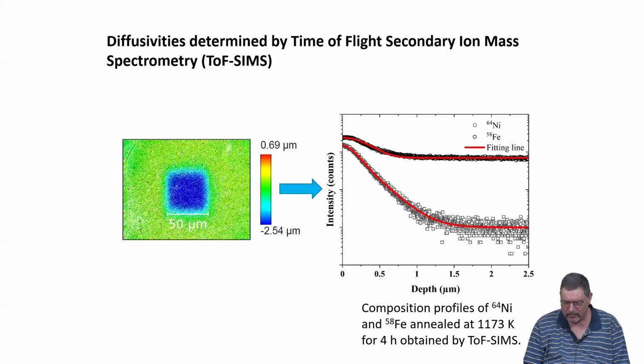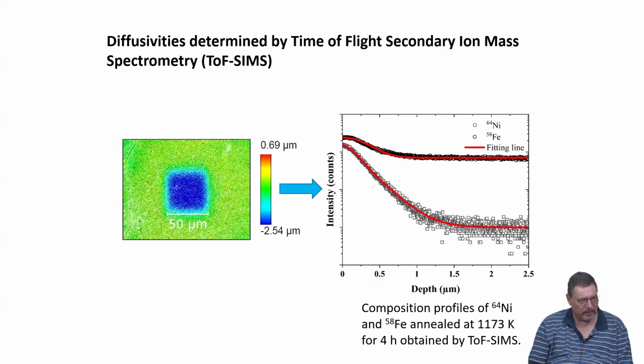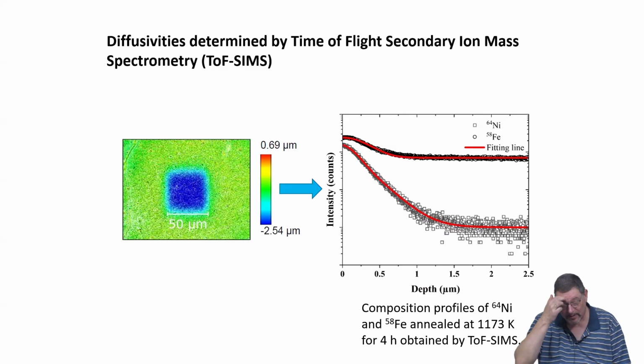So as a function of the depth into the sample, you get an intensity signal for every isotope present in your material, and then you just select the isotopes which you are looking at, specifically those you have applied on the surface. And you can also map this maybe with 2 isotopes, so we can later on map the ratio also, which basically gives you then a correlation which you can use in order to distinguish between different artifacts that could happen. Because the sputtering process in time of flight secondary ion mass spectroscopy also serves to mix the atoms, right? So you have some corrections which you need to do. Otherwise, the profiles work and are evaluated in a rather similar way.